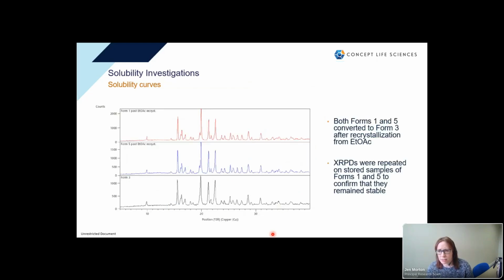So if I move to the next slide, here are just a few of our XRPD traces. The red one is form 1 after it's been recrystallized from ethyl acetate in the Crystal 16. The blue one is form 5 after it's been recrystallized from ethyl acetate. And at the bottom, we have our reference diffractogram from form 3. And you'll see that they are all the same. So at this point, we went back to our jars of form 1 and form 5, and we obtained new XRDs on them and confirmed that they were in fact still forms 1 and 5. They were stable in the jar, stable on storage, and they had both converted to form 3 during the recrystallization process.